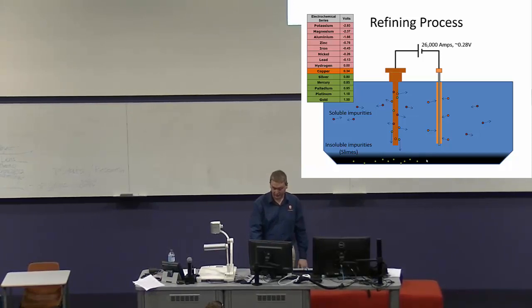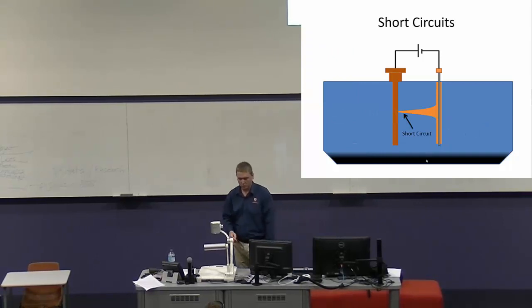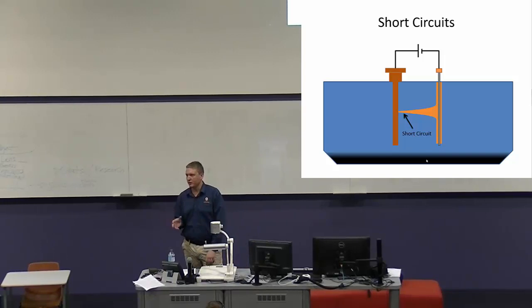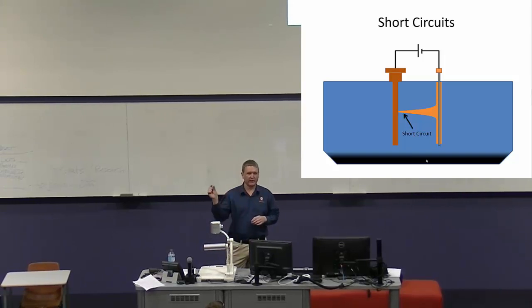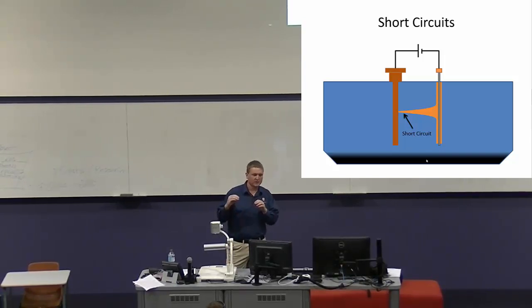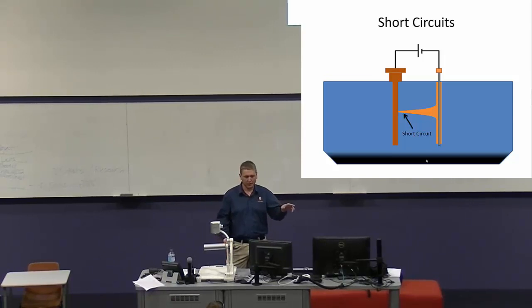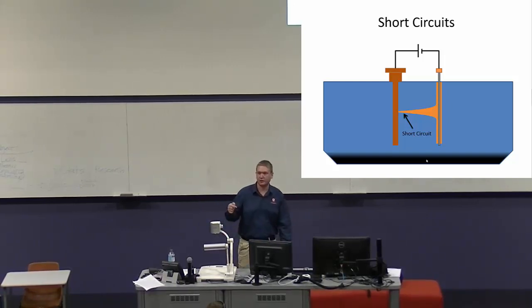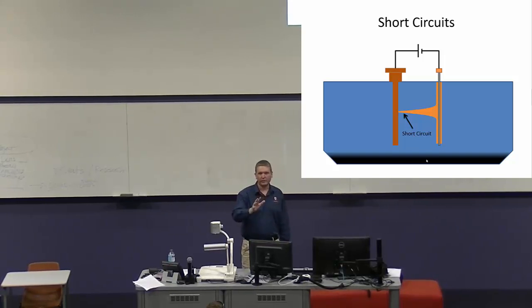That's the process of how we turn anodes into cathodes. One of the biggest problems we have is uneven growth on the cathode, forming what's called a short circuit. Our anodes and cathodes are only spaced about 20 millimetres apart. If the copper growth is uneven, you can get a spike of copper that eventually touches the anode. Once it does, electrons can simply bypass the whole electrochemical reaction — a superhighway that skips copper production entirely. That costs us money and efficiency.